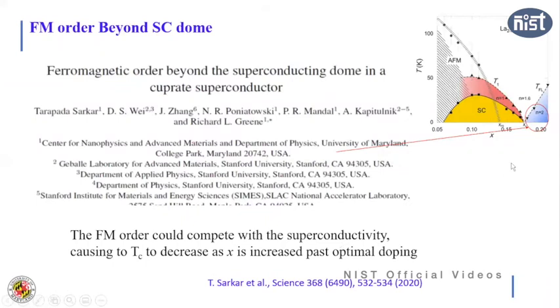Now this ferromagnetism in the regime beyond the superconducting dome is fundamentally very important because so far there is no explanation, only some speculation like the one I just mentioned, that probably spin fluctuation is the origin of why Tc is decreasing beyond the optimal doping. Since spin fluctuation is decreasing, that's the reason Tc is also decreasing. Now why does it end at some doping like 17.5% doping?